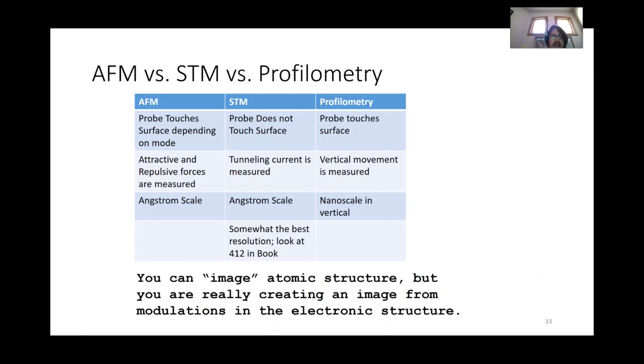If we look at the difference between AFM, STM, and profilometry, I always kind of like these tables. And so AFM, the probe touches depending on the mode. STM, the probe never touches the surface because you're dealing with tunneling, so you have to have a gap between your probe and your surface. And profilometry, at least for the classical definition, the probe touches the surface. For AFM, attractive and repulsive forces are measured. And so the electrostatic forces are measured, and in tunneling, STM, the tunneling current is measured, and in profilometry, vertical movement is measured. And there are some similarities again between profilometry and AFM, at least for contact mode AFM.